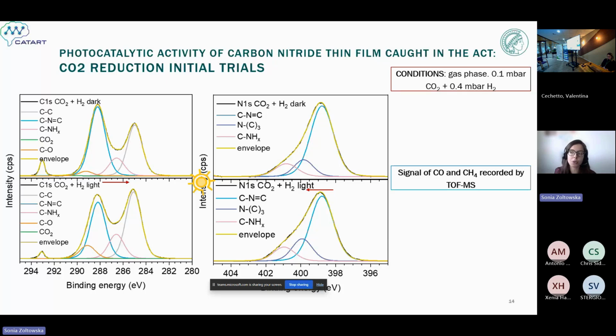Important to note is that we were also using TOF-MS located at the downstream end of the entire system, and we were able to track the signals coming from CO and methane at that moment, but that was a very preliminary study. We didn't make any quantification. We will do it in the next step of the research.